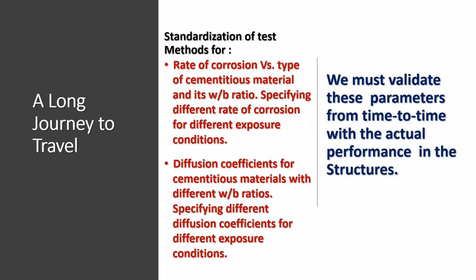I mean to say, there is a long journey to travel for the concrete. What is that journey? Standardization of test methods for rate of corrosion versus type of cementitious material and its water binder ratio, and specifying different rates of corrosion for different exposure conditions. Still, we have to develop these relations, and also diffusion coefficients for cementitious materials with different water binder ratios, and specify different diffusion coefficients for different exposure conditions.